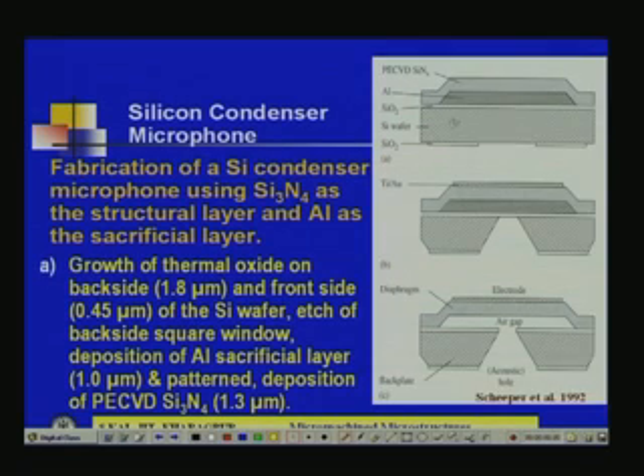First, a silicon wafer is taken, then you oxidize the silicon wafer. So, you can see the white region, this region and this region here. These are the thin layer of silicon dioxide which is shown here. After that, growth of silicon thermal oxide, back side and front side. Back side is 1.8 micrometer and front side is only 0.45 micrometer of silicon wafer. Etch of backside square window, you see you are etching backside square window here.